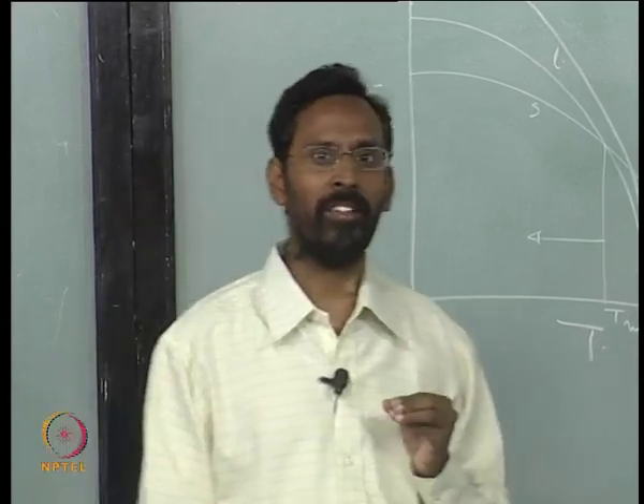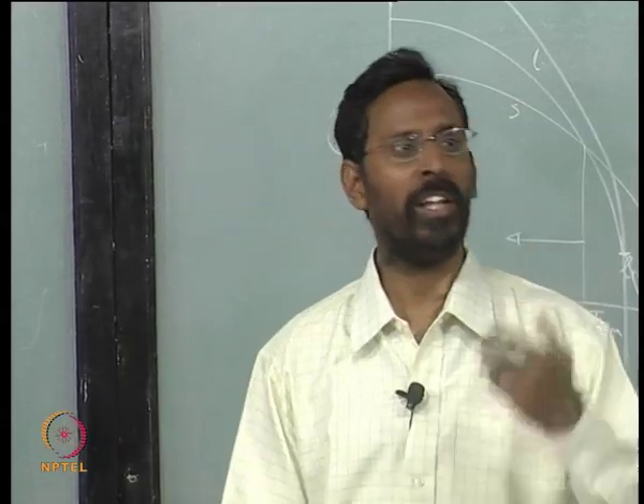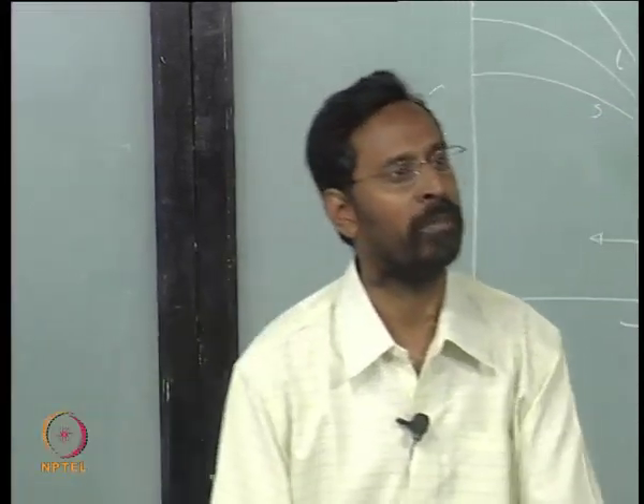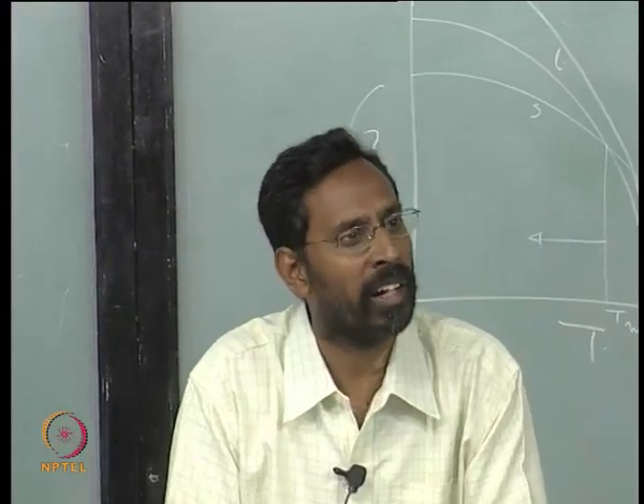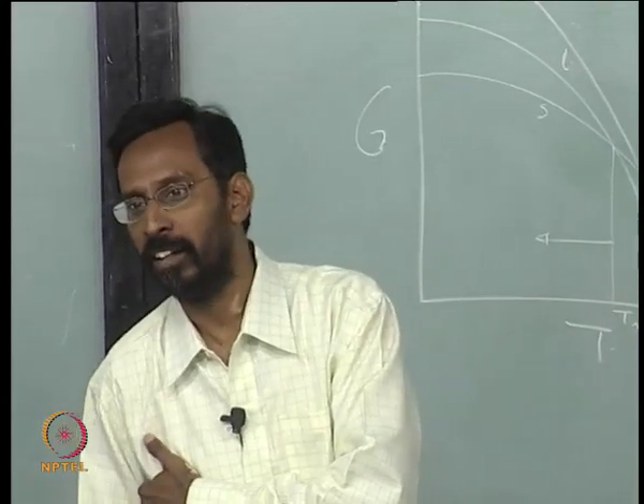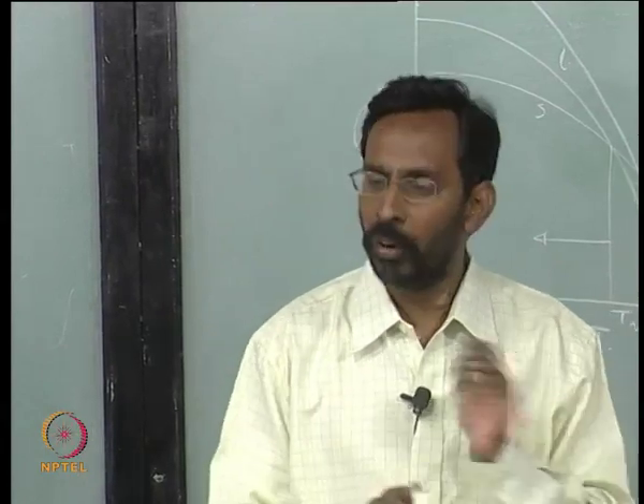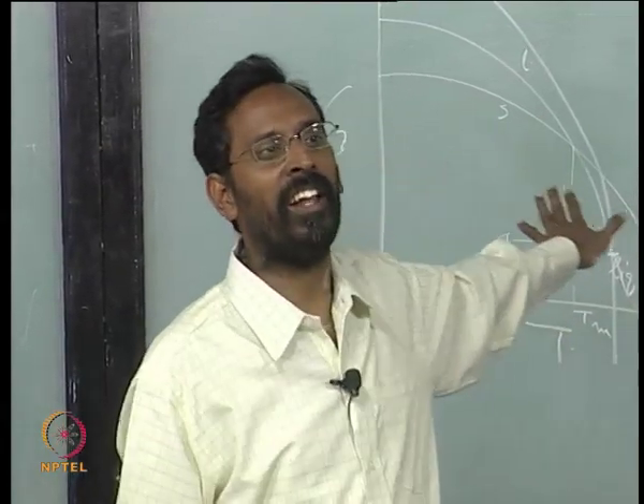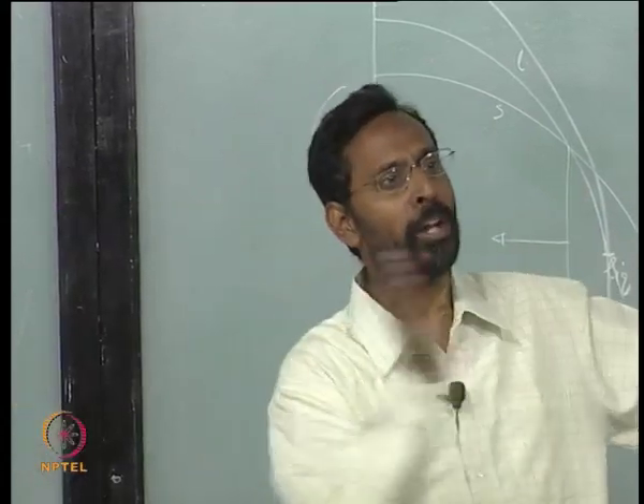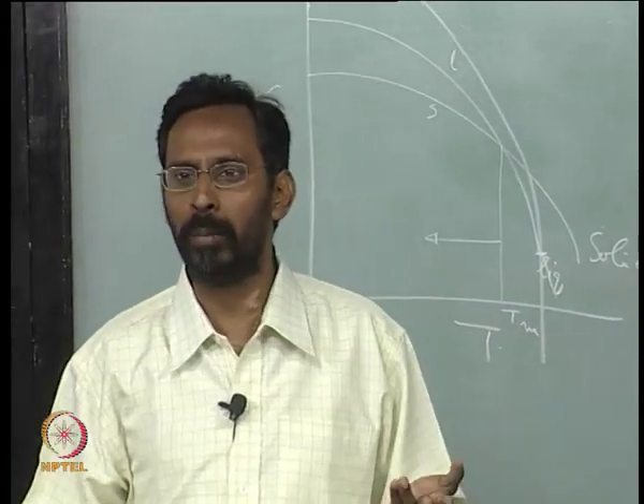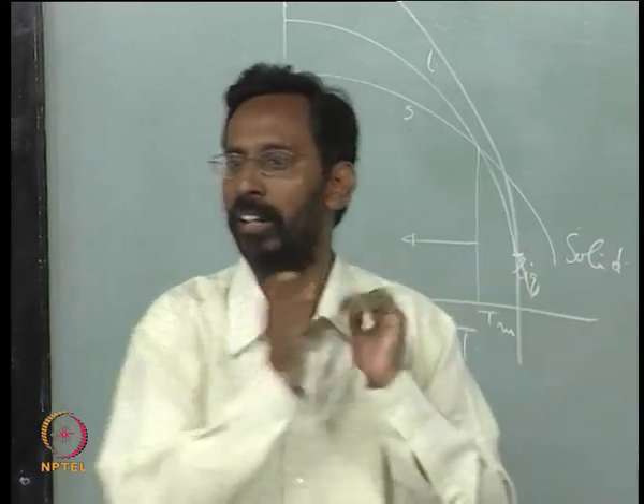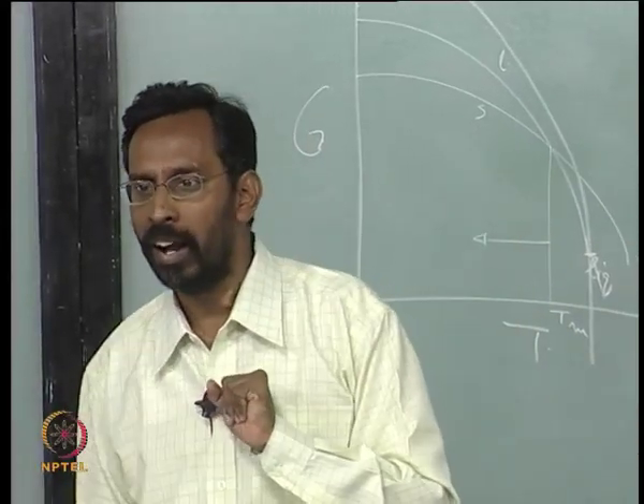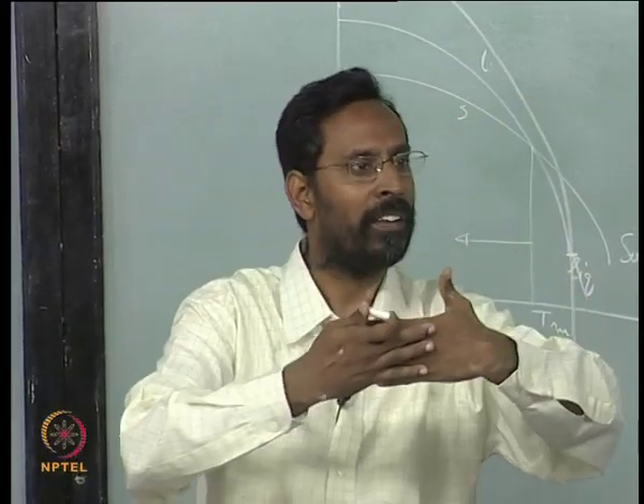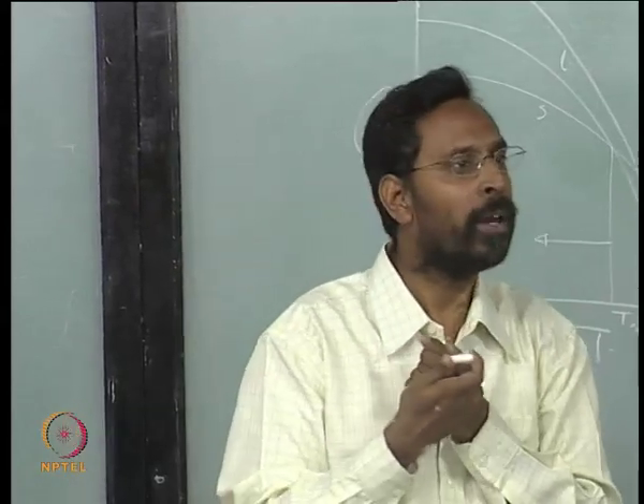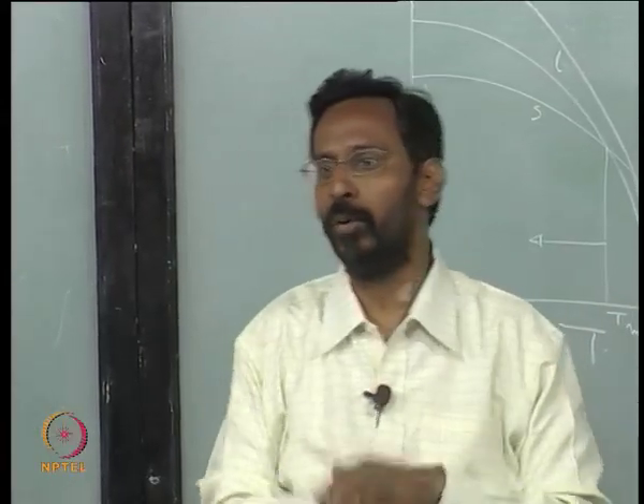Or in some cases the melting point of one of the metals is so high. For example, think of tungsten: I want to generate the aluminum tungsten phase diagram. How do I do it? I cannot melt tungsten, I do not have crucibles available where I can melt tungsten, because its melting point is 3400 degrees or so. So the only way in such cases is this kind of calculation. I can generate the phase diagram on the aluminum side, because aluminum can be easily melted. So on the aluminum side you can generate it experimentally, do thermodynamic calculations, and see if the phase diagram from the calculations fits well with the experimental one. If the fit is good, then you get confidence in the thermodynamics, and then assume that I can extrapolate it towards the tungsten side.